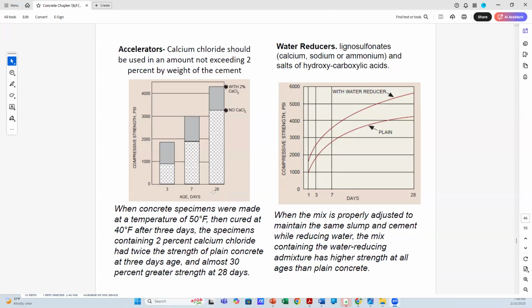These are some statistics behind what you can do to get high strength with less water. So as you add plasticizer into your concrete, it delays the curing a little bit longer, but you reach even higher strengths. With what plain concrete can achieve, let's say 4,200 PSI, the same concrete with plasticizer can get to 5,500 PSI, a lot stronger building.